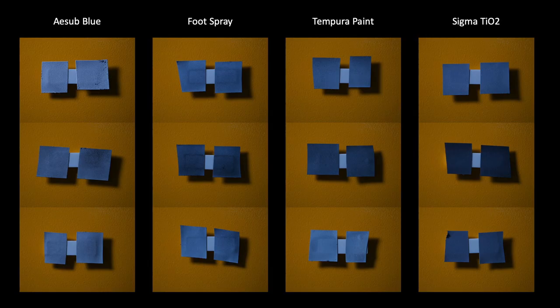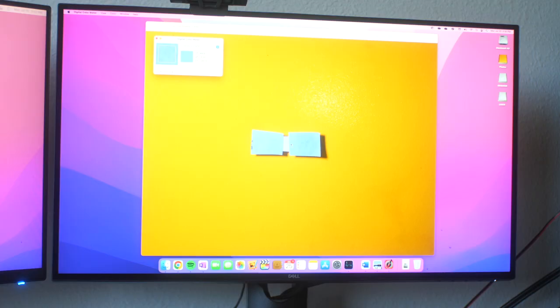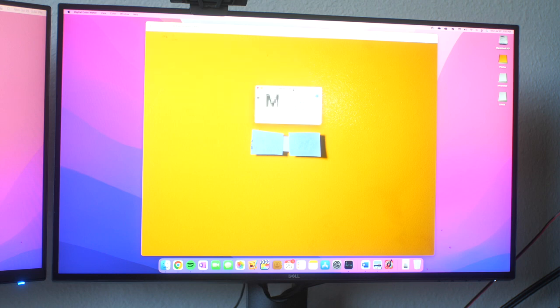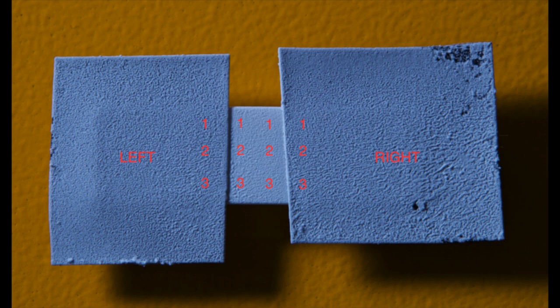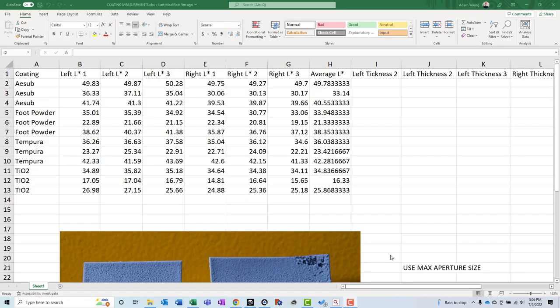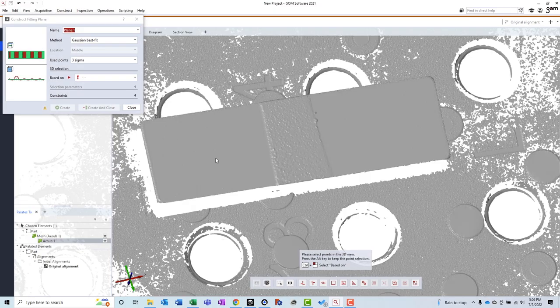After performing each of these tests on each coating type, I then performed them all again two more times for each coating type, trying to vary the thickness for each test. After all of these tests were complete, I moved into the analysis portion of these tests. To evaluate the lightness of the coating, I used the digital color meter application found within macOS to evaluate an L value at 6 locations immediately beside the untaped portion of the gauge block. I then averaged these measurements and paired it with the coating thickness and flatness.